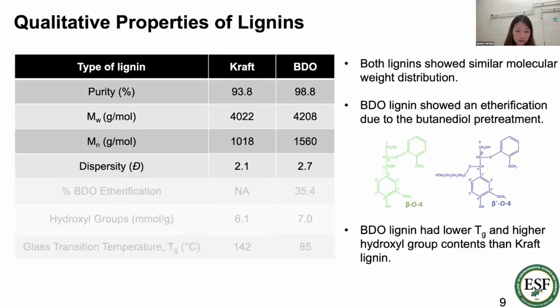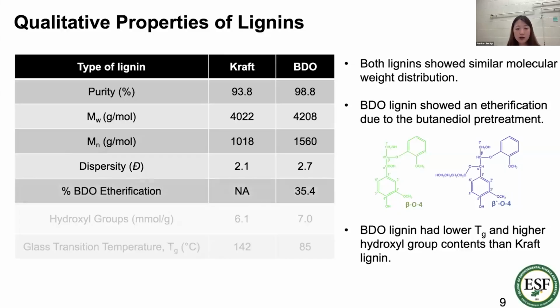However, interestingly, the BDO process has etherification, BDO etherification, during the biomass pretreatment. So there is some etherification, 35% etherification showed up in the BDO lignin structure. And also we wanted to see how much hydroxyl group can be replaced by etherification. The hydroxyl group measurement shows that the aliphatic and phenolic hydroxyl group content is quite similar between kraft and BDO: 6.1 millimole per gram for kraft lignin and 7 millimole per gram for BDO lignin.